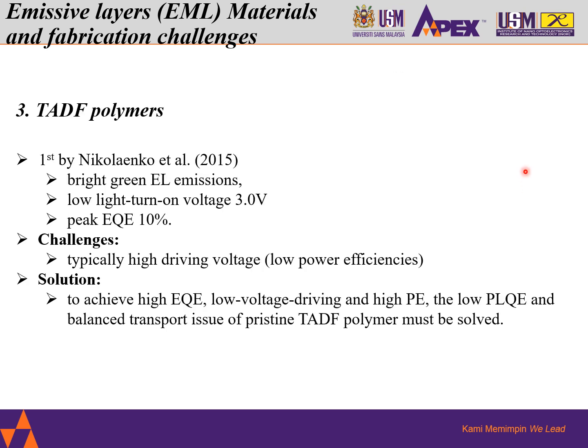TADF polymers. The TADF polymers were first realized by Nikolaenko in 2015. These types of PLED showed a very bright green EL emission, a low turn-on voltage of around 3 volts, and a peak EQE of 10%. However, the drawback of TADF polymer PLEDs is typically high driving voltage, and thus lower power efficiencies. In order to achieve high EQE and low voltage driving of TADF PLEDs with high PE, the low PLQE and balanced transport issue of pristine TADF must first be solved.